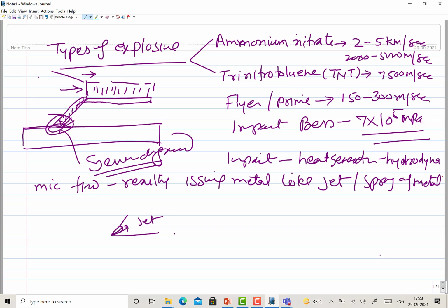and then it will be covered or enclosed. This spraying will lead to scouring, removing the surface impurities. At the same time, it will lead to the formation of the jet like this. That is what you can easily see. There are different situations. Jetting is one typical situation, otherwise the interface may be perfectly flat as well.